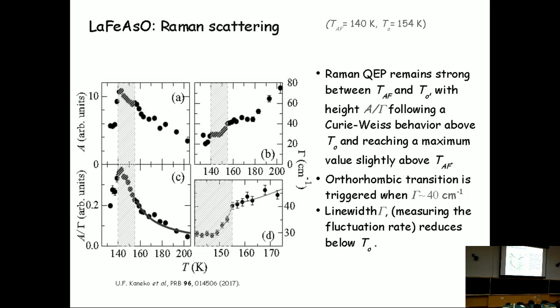Further questions? There's one here. It's just a minor point. I think what you're saying is that based on these results, one cannot conclude that the electronic mechanism is actually driving the structural transition, right? Because then they would have to occur together. Yes. Right. So that means, at least in this compound, the structural transition is maybe driven by the structural transition itself and not by the electronic mechanism in the first place. Is this a correct interpretation?